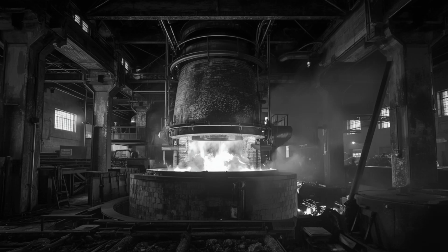The second theory is structural collapse, a progressive failure of the internal refractory lining, crushed under its own weight and the pressure of the iron column inside, settling downward and dragging the outer shell with it. But the furnace continues to operate normally. The iron quality remains consistent. The internal temperature profile, inferred from the color and behavior of the flame at the top and the composition of the slag, shows no signs of lining failure. If the refractory were collapsing, the furnace would be hemorrhaging heat, producing inconsistent iron, showing visible distress. It does none of these things.